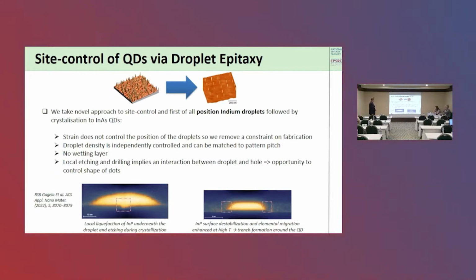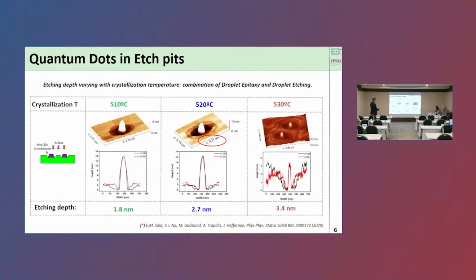And this is actually interesting because it opens up the possibility for us to shape the dots. Going back to the idea of symmetry of dots and having very small fine structure splitting for entangled photons, the more we can shape dots, the better. We think that the ability to match this etching and drilling to the nanohole itself is an opportunity for us to look at controlling the shape of the dots.